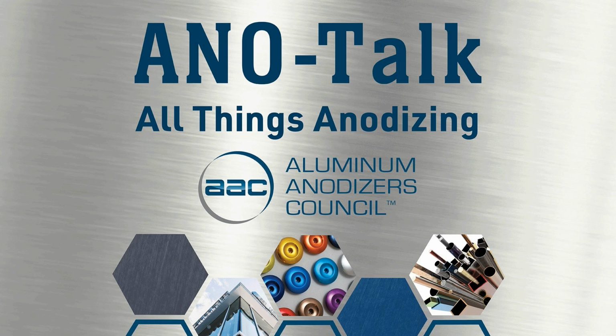In many ways, if you're doing the pulse anodizing right, you will actually have a little lower voltage compared to conventional direct current, because you are teasing your interface between the aluminum and the aluminum oxide, which helps decrease the overall voltage. So that's the reason why there is an energy saving during the process, together with the productivity saving.